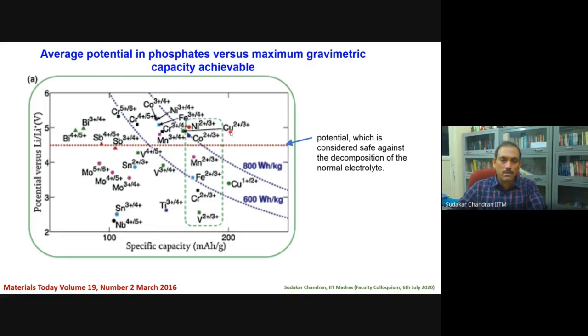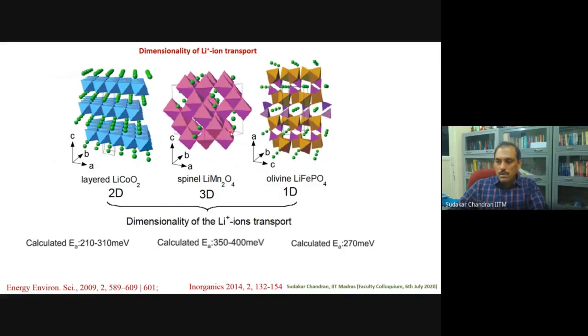reduction and oxidation reactions. So came three different materials from Goodenough's group. They had very different characteristics in terms of the dimensionality of the lithium ion transport. In LiFePO4, the polyanion compound, lithium moves in and out in a one-dimensional fashion. The layered compound has a two-dimensional lithium diffusion, whereas the spinel LiMn2O4 has a three-dimensional diffusion.